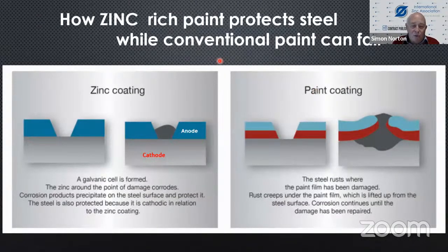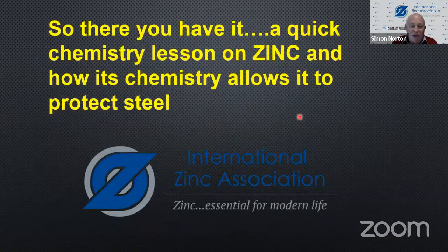Now, Graham Stead's going to be talking about zinc rich paints, but I'm just talking about the chemistry of it. You get an anode and you get a cathode, and you've got a hole in a zinc coating. The zinc then forms materials, zinc oxide, hydroxide, zinc carbonate, and this little hole fills up. And by this action, eventually the coating protects the underlying material. If you only have a paint, a conventional, ordinary, run-of-the-mill paint, when the paint cracks or is damaged, then you've got the steel exposed to the atmosphere, corrosion forms, the paint then is peeled away, blisters and comes away, and the life of your machine, product, whatever it is, is shortened. So there you have it, a quick chemistry lesson on zinc and how its chemistry allows it to protect steel.